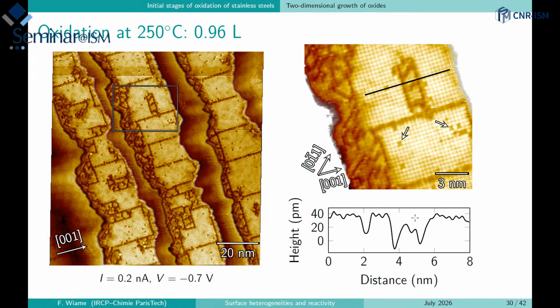So once again, I have leveled out the plane just to see what we have on the terraces, and you can see the atomic resolution on the terraces, where now we have the surface, the place where there was the chromium nitride, which is now completely modified with the formation of chromium oxide. We have also some defects which are appearing, which are in fact chromium atoms which are extracted from the terraces and which are, we think, brought by these vacancy lines to this area on the step edges where they are more reactive. We sometimes have some modification and formation of defects and vacancies of chromium on the terraces, but most of the reaction is still continuing at the step edge, which is generally a more reactive site.